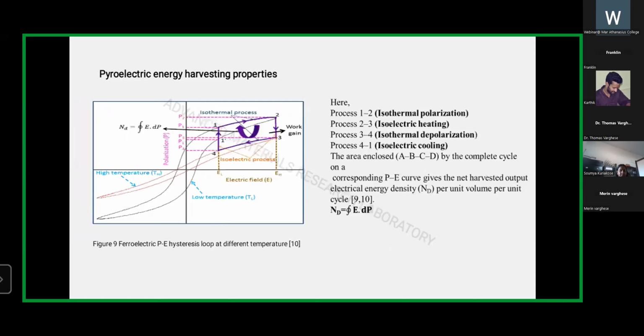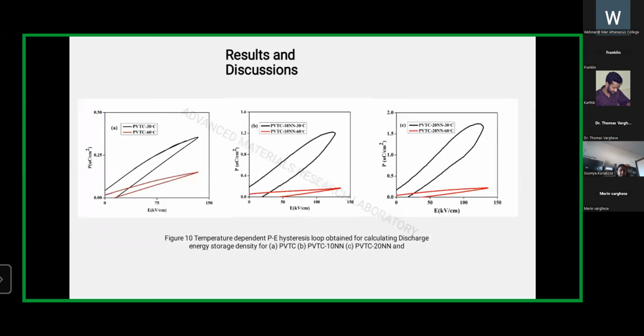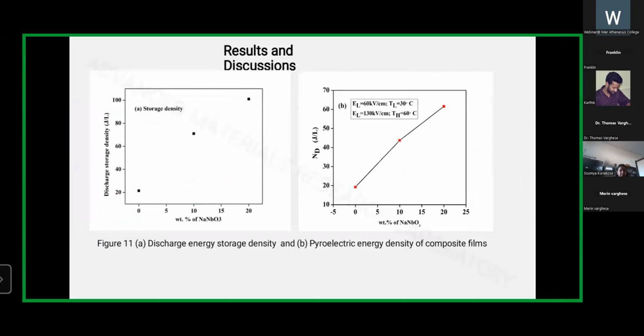And in another approach, the energy harvesting studies were also done. That is a thermodynamic approach. Here also ferroelectric P-E hysteresis loops were used to study the pyroelectric energy harvesting property. And here, 2 hysteresis loops are obtained for 2 different temperatures, and the area enclosed by the loop is used for calculating the energy harvesting density. And this is the pattern that is obtained for the composite films. So we can see that here also the polarization of the nanocomposite films is changed for different temperatures, and this change in polarization is used for calculating the energy harvesting density using the pyroelectric method. And this is the comparison of the results that are obtained.